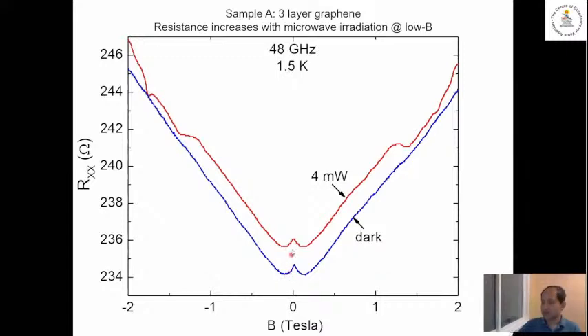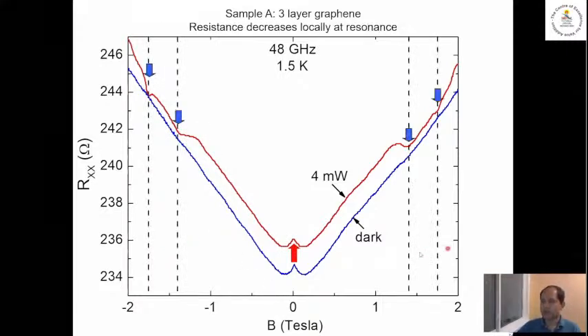So this is similar to the heating effect. When you heat the sample, resistance goes up. When you apply microwaves, resistance goes up. But then at some places in the magnetic field, the resistance drops back down. It's like local cooling, and there are 2 places where it happens, here and over there too. So apply microwaves, resistance goes up, and what we call resonance is where the resistance comes back down. So there are 2 resonances, one at positive magnetic fields and one at negative magnetic fields.